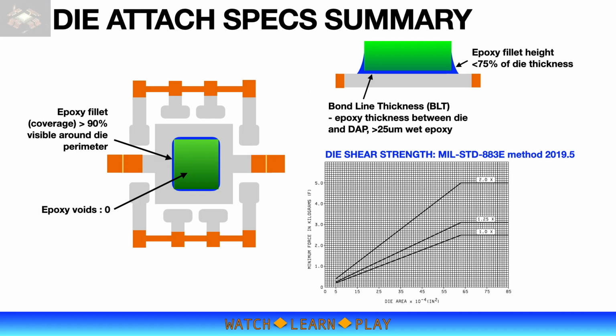Just to recap the attach process specifications. Epoxy coverage must be 100% with visible epoxy of more than 90% on each side of the die. Epoxy fillet height must be controlled at less than 75% of die thickness to avoid epoxy contamination on die surface. Epoxy on die manifestation is considered a reject.